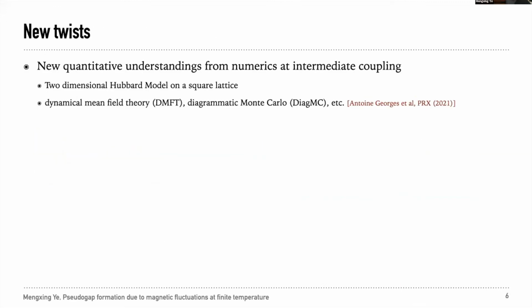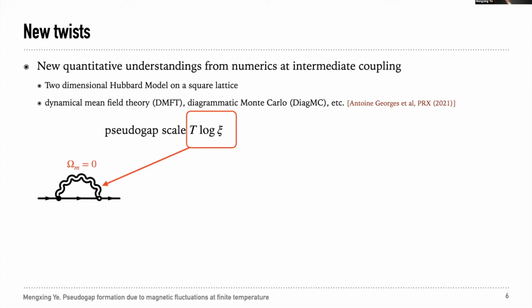Okay, so now let me tell you a bit more about what motivated us for this current study. One motivation is from the recent numerical studies on the two-dimensional Hubbard model on the square lattice, such as DMFT and diagrammatic Monte Carlo at intermediate coupling, which give us new quantitative understandings. Let me quickly review the findings there. First, it can be shown that the pseudogap scale is proportional to temperature times the log of the spin correlation length. We can easily understand this energy scale by just considering a Fermi liquid interacting with some static magnetic fluctuations at second order perturbation.